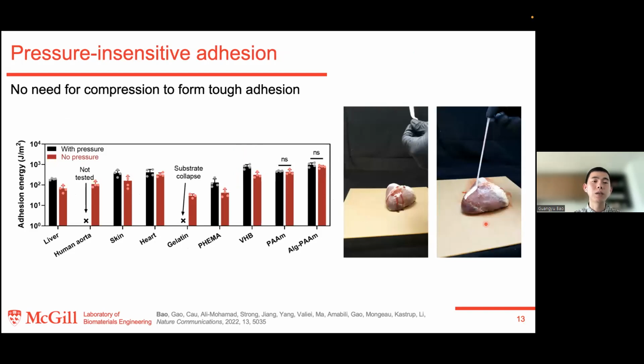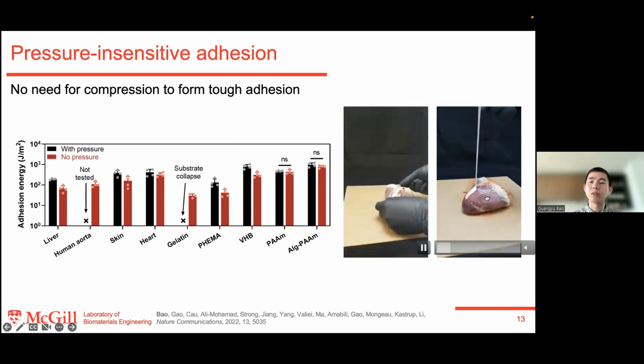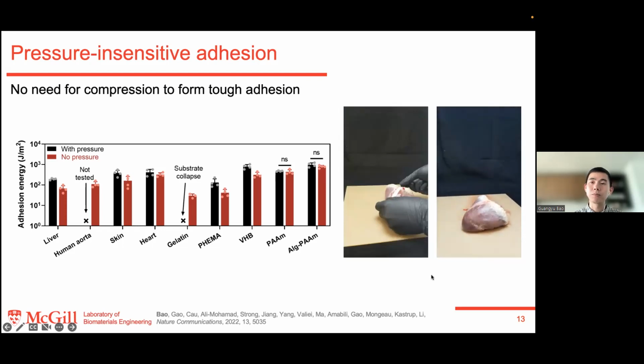And unlike many bioadhesives that require compression, our adhesive can adhere to a variety of blood-covered surfaces without the need for applying compression. For some delicate surfaces, such as the gelatin here, even applying compression can collapse the substrate. In this demo, you can see that we first put blood on top of the porcine heart and gently placed our adhesive on top of the heart. During the peeling, you can see the adhesion formed very quickly and also strongly on the heart surface.